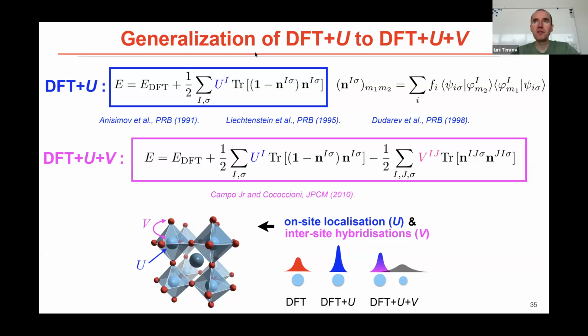So yes, if you have two researchers, let's say you use Quantum Espresso with atomic orbitals, and you get Hubbard U of 5 electron volts. And your colleague uses another code, let's say VASP, with a different type of projectors, not atomic, but a more complicated type. And your colleague obtains, instead of 5, let's say 6 electron volts. You both study exactly the same material, let's say iron oxide, but you get 5 and your colleague gets 6. So who is right, who is wrong? The answer is nobody.